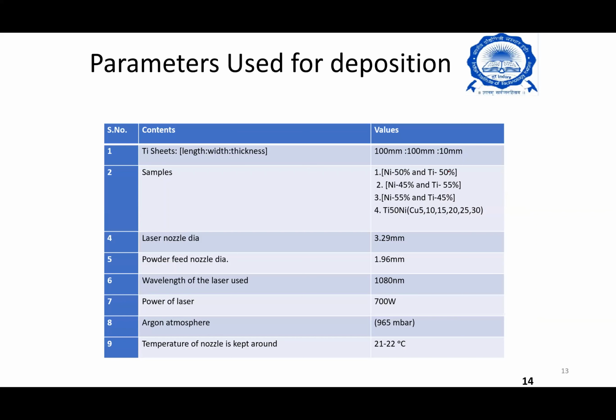So basically we took a 1:1 ratio of nickel titanium. There are 3 different combinations with 3 different powders. Our main prime focus is to check the composition capability, that is, with respect to variation in composition, how does it behave? So there are 3 different NiTi compositions with 3 different weight percentages: one is NiTi 45-55, another one is NiTi 50-50, and another one is NiTi 55-45.